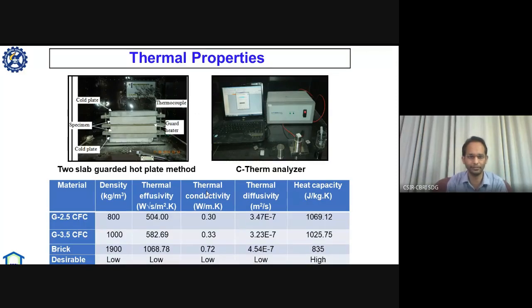And we have also seen the thermal properties through the transient state method and the C-Therm analyzer. For grade 2.5, like we denote M20 or M25 for conventional concrete, here M will not work, here G will work. So G 2.5 CFC and G 3.5 CFC, and we have compared different properties related to thermal behavior with brick. You can see here the density was just half for G 3.5 and quite less for 2.5, and just see the thermal conductivity, because we are more concerned about thermal conductivity.